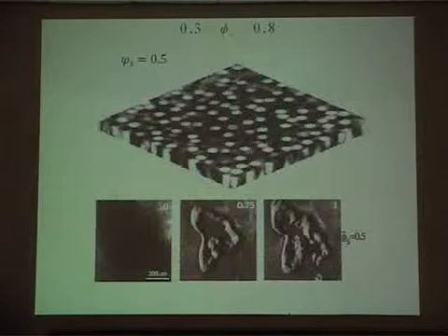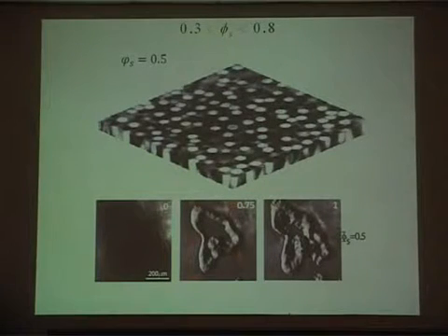Okay. So this happens. Suppose I take a 0.5 volume fraction of silica and polystyrene mixture. Then the failure event is very different. Then you start having blisters in the system. These are the blisters which you actually see. If you go outside, you will see blisters on the wall because they are polymer paints with colloidal particles loaded in. And when they fail, that's because moisture has gone in, and with time they have placed stress in it.